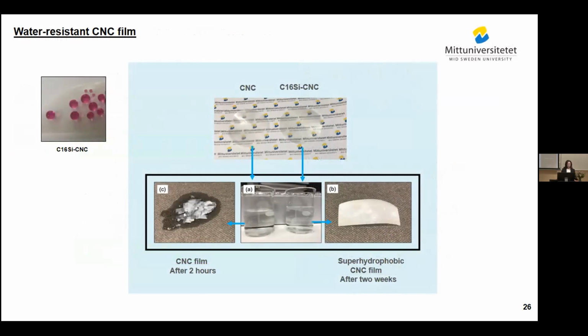I wanted to see the water resistance of this modified CNC film. So I soaked both the unmodified and modified CNC films in water. After 2 hours, the unmodified one was totally disintegrated, while there was no change in the modified one. I kept it for an additional 2 weeks, and after that, this is the result. It means that with the modification, I could get a highly water-resistant CNC film.